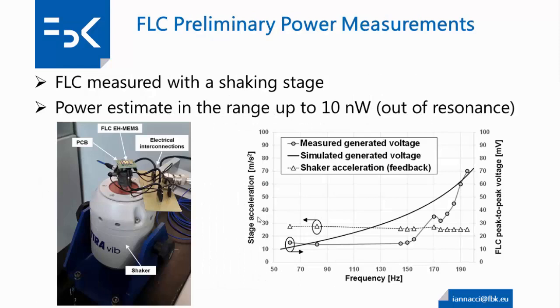The last slide concerns the preliminary comparison of power output. The power we observe is very low, because the measurement setup was still being developed and we managed to measure the device only at very low frequency — out of resonance. Also, devices from the first fabrication batch had problems with aluminum nitride leakage. So the purpose of this graph is more to validate the ANSYS Workbench coupled-field analysis tool including the piezoelectric effect, rather than to validate the actual performance of the device, which is what we are currently working on.